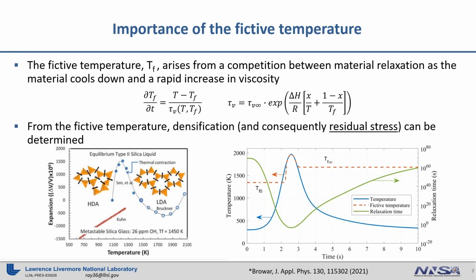And so to better understand that, there's a concept of fictive temperature that we really need to take a moment to explain, because that's going to come back up over and over again. And so the bottom left plot is the expansion of fused silica as a function of temperature. And fused silica is an interesting material. If I bring your attention to the curve with the blue dots, when you heat it up, initially it expands, as you would expect material to, but then there's an inflection point.